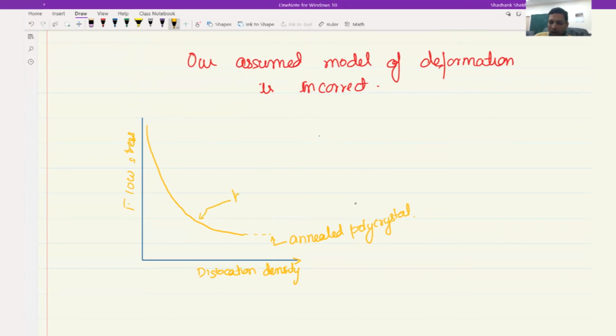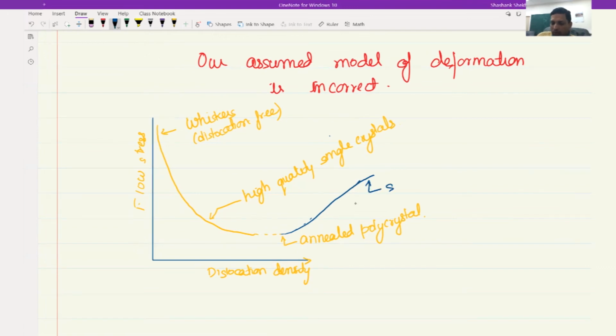Somewhere here, you would have high quality single crystals. And here you will have what are called whiskers. So these are mostly free of dislocations, or nearly free, I should say. So when you don't have dislocations, then the flow stresses are very high, orders of magnitude higher, close to the theoretical strength that we have come to expect. On the other hand, if you keep increasing dislocation density in this direction, then what we get are strained or work hardened alloys.